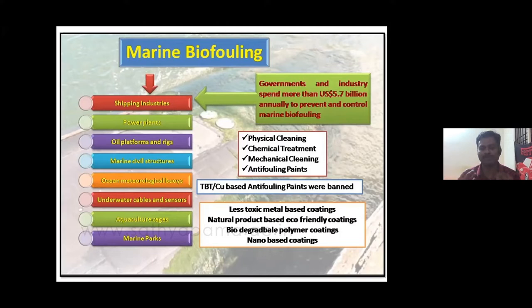But the problem is the TBT slowly will leach out, and it accumulates in the marine environment, and it has the tendency to cause imposex in marine organisms. One of the molluscan varieties is reported to undergo sex reversal, which is called imposex, because of the TBT, tributyl tin. So the International Maritime Organization as well as the Maritime Treaty completely banned these TBT based paints,